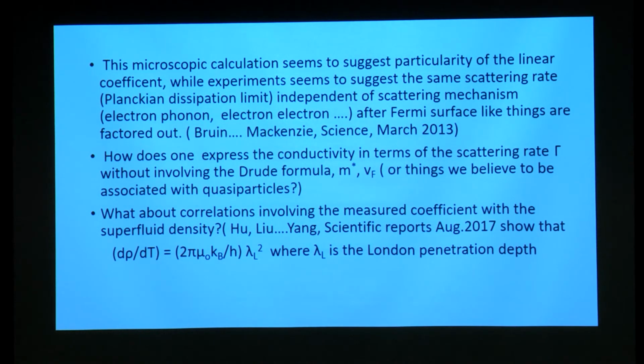And using those numbers, and using, let us say, the Drude-like formula, they express the conductivity in terms of the scattering rate, and that scattering rate turns out to be linear in temperature. So that is one kind of experimental correlation which has been seen. They also found that the resistivity of ordinary metals due to electron-phonon scattering, which is also linear in temperature, again follows this universal limit. So it's not very clear what is happening.